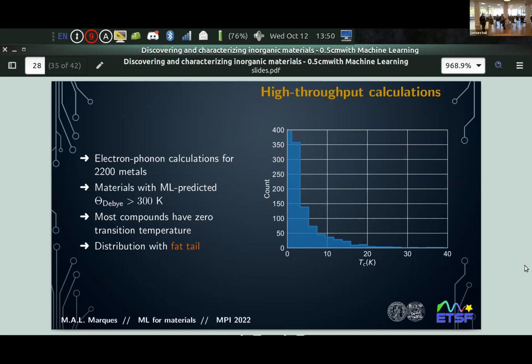And the objective is, of course, to study all. And here's the distribution of TC. And again, this is cut at 0 because obviously most compounds are not superconductors or have very, very small superconducting temperatures. And what do you see? A fat tail. Again, yeah? Even in conventional superconductivity. I will show you in more detail some of the results actually, but you see the scale goes to around 40 here. Okay, magnesium diboride is around 40 also.